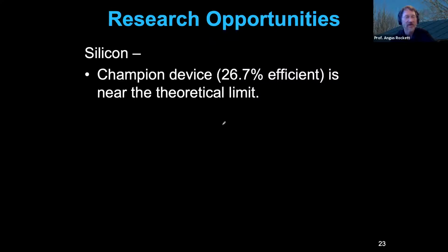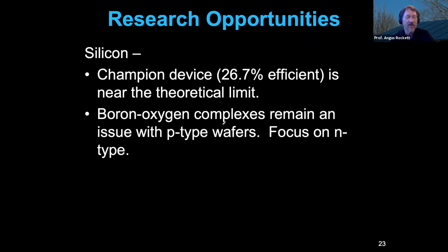Well, one of the things that you find with silicon is that when you run a silicon solar cell, you tend to have so-called potential-induced degradation, and that's often related to complexes of boron and oxygen. And this is in particular when you have a so-called P-type silicon wafer. So one approach to dealing with this is to change to N-type silicon wafers that you build the devices out of. But there are advantages and simplifications when you use a P-type wafer.